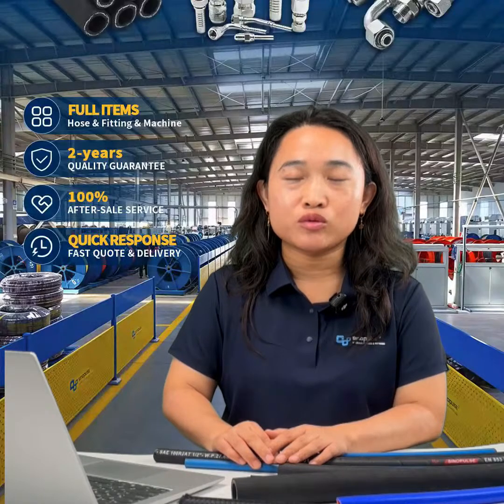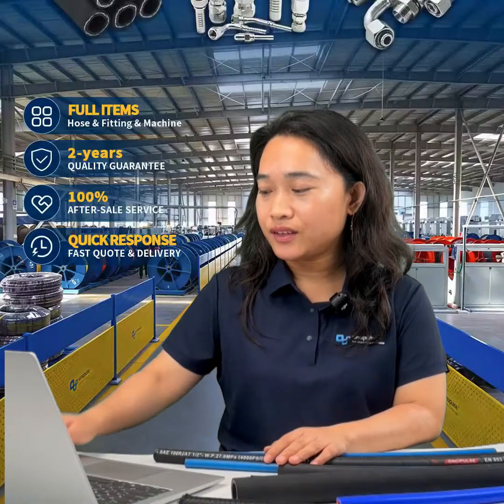Okay, then we come to the finished hose in our factory after production. What tests do we do? First, during production, we test each hose with 1.8 times working pressure for 60 seconds, to make sure each hose is without any leakage before shipment to customers. And after hose production, what tests do we do? We test the burst pressure. We test the impulse. We choose the hose samples from our customers' orders. We test the burst pressure, and our hose burst pressure is higher than the standard requirement.